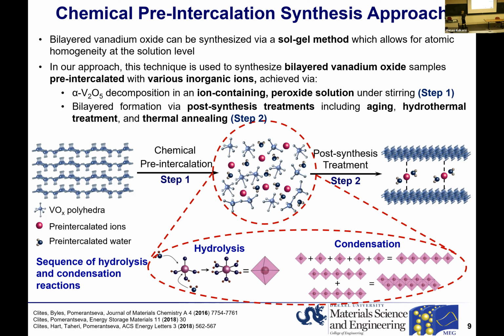So essentially, I'm going to be using this vanadium oxide system as an example to explain the synthesis. Alpha V2O5, which is also a layered vanadium oxide material, but with a much smaller interlayer distance, is used as a precursor. It's dispersed in water, and hydrogen peroxide is added. What happens is a sequence of hydrolysis and condensation reactions. First, these complexes between vanadium, oxygen, and hydrogen, tetrahedral complexes, undergo nucleophilic attack by water molecules and convert into octahedra. And then these octahedra grow together, forming chains. And then the chains also grow together, forming bilayers.